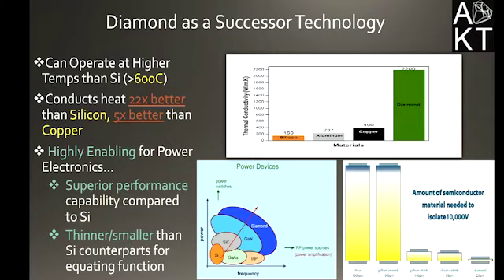But even more important, it's highly enabling for power electronics, where we have superior performance as compared to silicon. We can drive it at higher frequencies. We can switch very quickly, much higher loads of power. And we can do that utilizing thinner and smaller layers and feature sizes as compared to the silicon counterpart for the equating functionality. And here we compare diamond to the other wide band gap materials. And we can see diamond is far superior as compared to even gallium nitride, which is seeing more increased use in the marketplace. And in terms of the material thickness, far less diamond is required to isolate large voltage as compared to the other materials, and especially as compared to silicon.